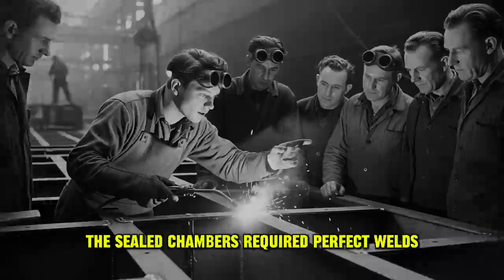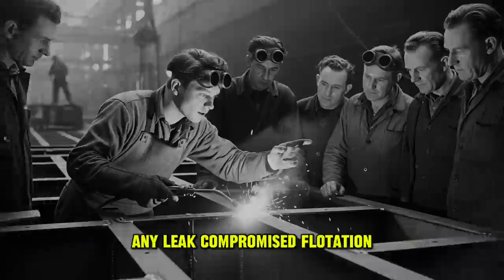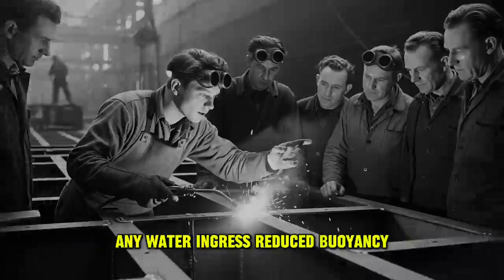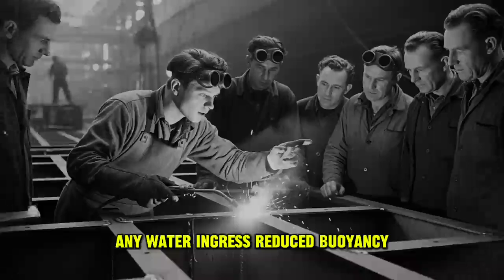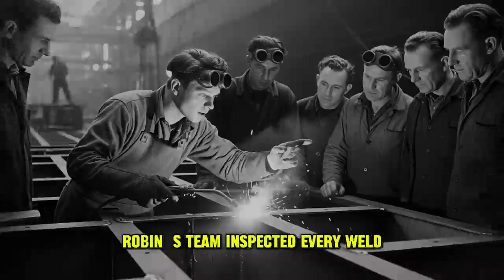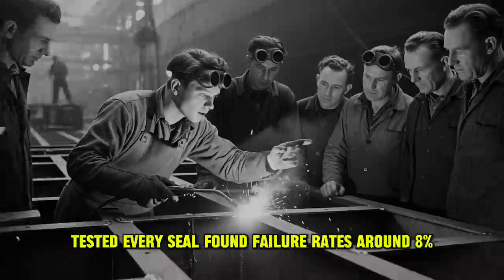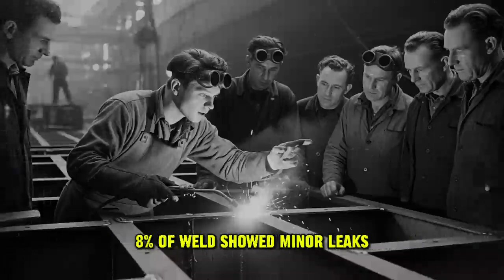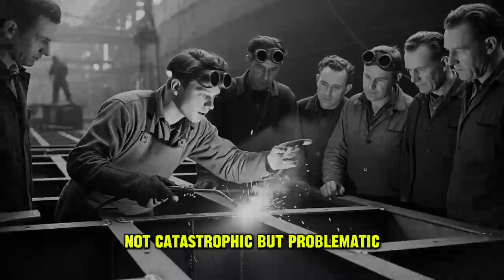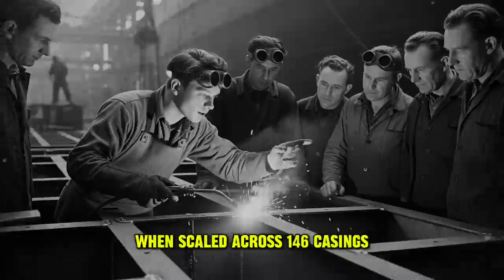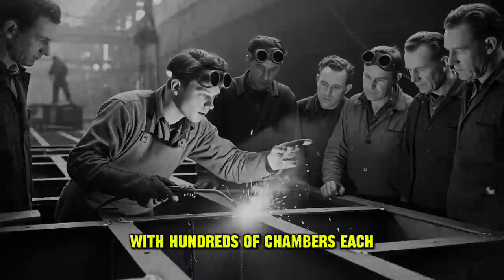The sealed chambers required perfect welds. Any leak compromised flotation. Any water ingress reduced buoyancy. Robbins' team inspected every weld, tested every seal, found failure rates around 8%. 8% of welds showed minor leaks. Not catastrophic, but problematic when scaled across 146 casings with hundreds of chambers each.